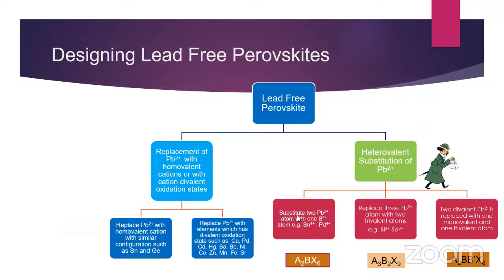So the heterovalent substitution of lead can be done by substituting two lead atoms with one tetravalent B4+ atom such as tin and palladium, and you can also replace three Pb2+ atoms with two trivalent atoms, and you can also replace two divalent lead atoms with one monovalent and one trivalent atom.